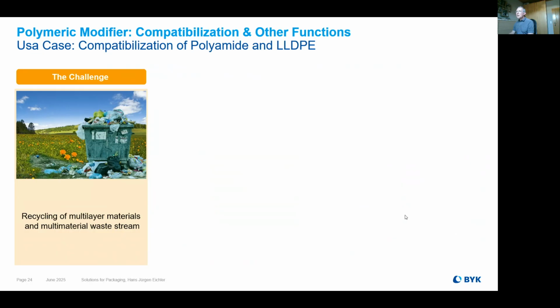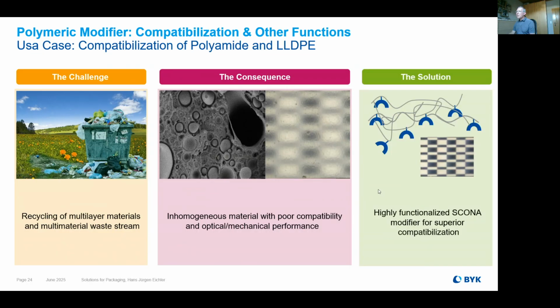So if we look now at a use case of these compatibilizers, you still know that the recycling of multi-layer materials is really hard work to do. And to overcome these issues, especially if you have this big mixture of different stuff, you get something which is inhomogeneous and has poor compatibility. It is very poor in optical or mechanical performance if you want to make films again out of that. And our solution is to work with these functionalized Skona modifiers, which work as a compatibilizer.